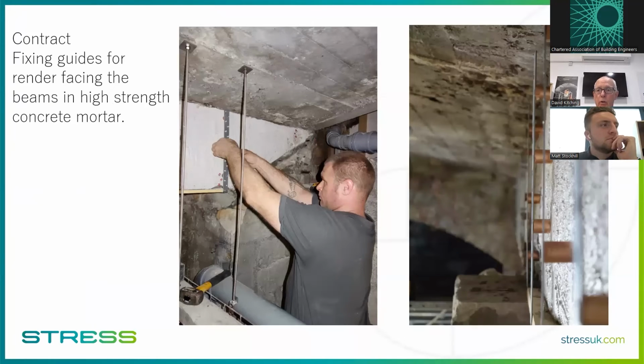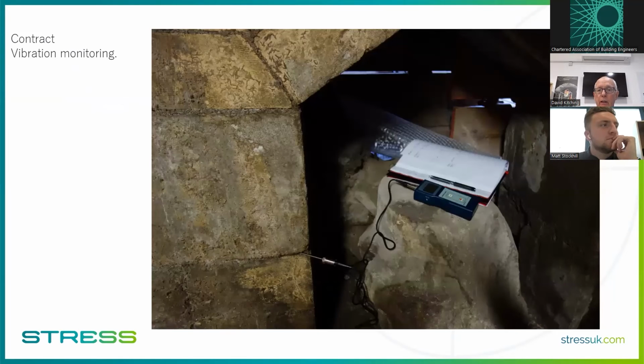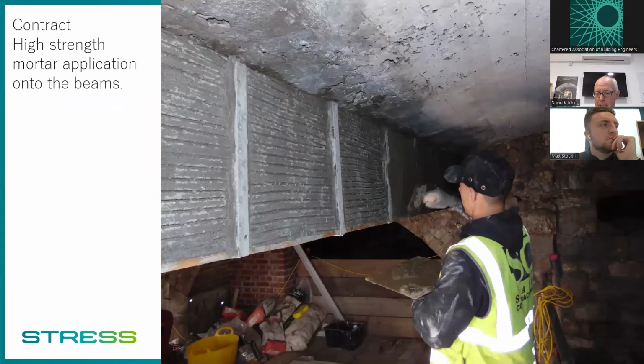The system, however, was to put two steel sections either side of the existing composite steel beams. And what we found was that, in fact, the Victorians didn't really care just how good the surface of that concrete was. So it had to be evened out vertically, so that we had our two C-sections normal to each other. And so we put up guides with a laser detector, and we could then repair the concrete to that exact face, so that you've got a full, good distribution of load from the beam through into the steel.